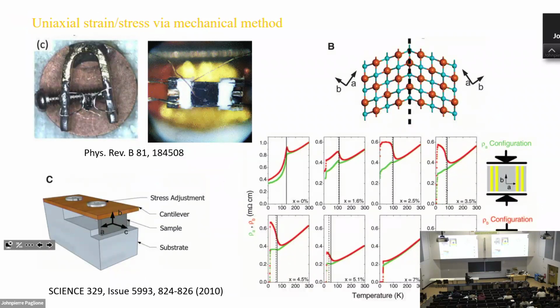One of the early examples is the iron-based superconductor. At higher temperature, its structure is tetragonal, and at lower temperature, it turns into an orthorhombic structure. So A and B are no longer the same. However, if you just measure the sample, you don't see any anisotropy, because when it transforms, it has domains. In some regions A is here, in other regions A is here. So on average, if you measure anisotropy, you don't see any. So this is why people want to use strain to detwin the sample.